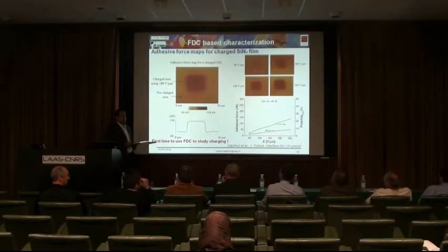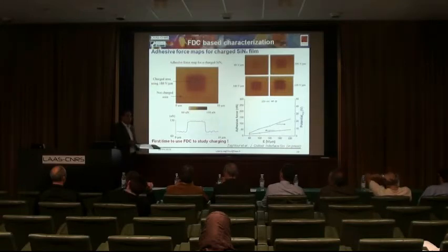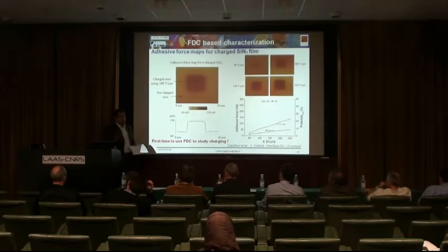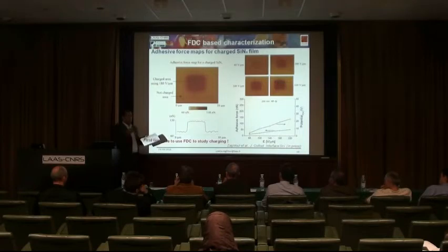But even for such kinds of tips, the available information is not really accurate. When they give you the spring constant, it is given as 1 to 6 Newton per meter. There are some techniques, of course, like a very famous paper from Dr. Bouchon where you can calculate it directly, but this is a point of issue. The calibration with such kinds of measurements is extremely horrible.